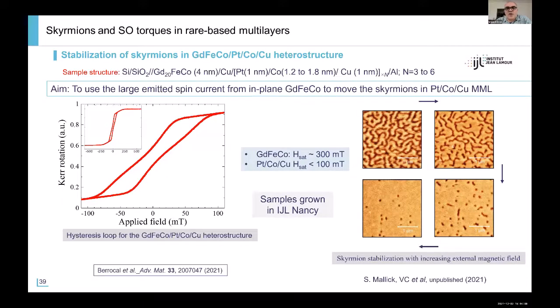Also, another work on ferrimagnetic systems is in collaboration with Carlos Rojas Sanchez from Institut Jean Lamour and Nancy. Sugata Malik prepared some systems here, containing both this skyrmion multilayer, platinum, cobalt, copper in this case, but then separated by copper from a ferrimagnetic layer that in this case will be used as a large emitter of spin current, because we demonstrated recently in collaboration with Nancy that we have a large charge to spin conversion effect in this motion.